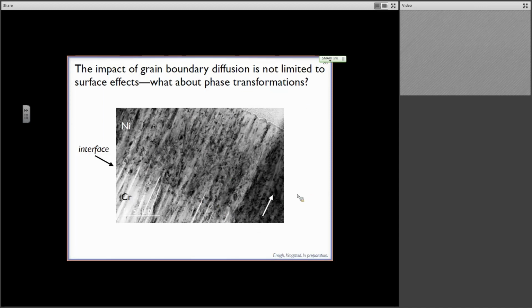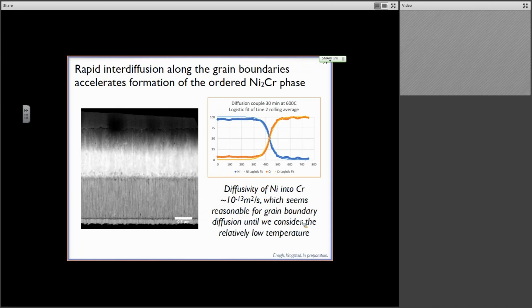And what we've done here is start making these nano or micro diffusion couples. In this particular case, I've got a layer of nickel on top of a layer of chromium, which is interesting for a lot of other reasons that I don't have time to talk about today. But then we can actually perform a traditional diffusion experiment where we have the nickel diffusing into the chromium and the chromium diffusing into the nickel, and we get these nice interdiffusion profiles. We can use a very traditional Boltzmann-Matano sort of approach to deconvolute this data and extract the actual diffusivity.